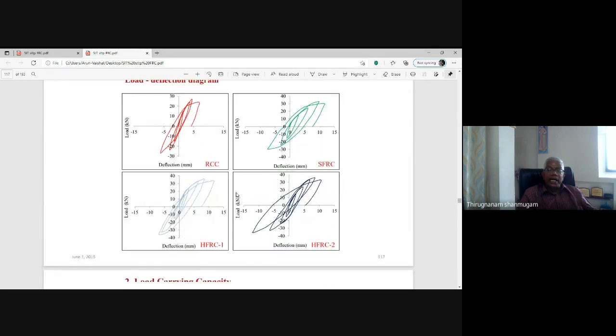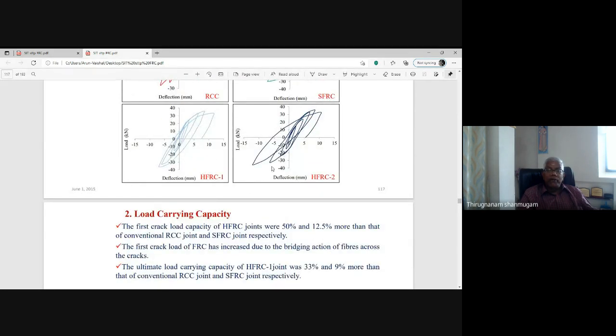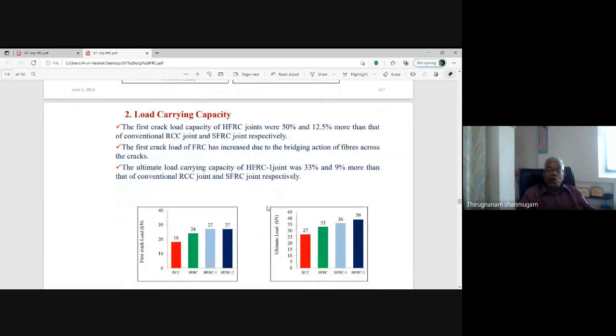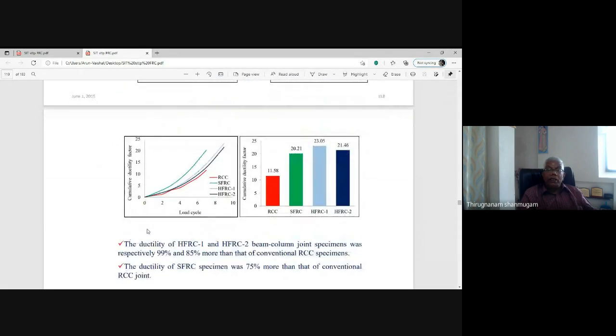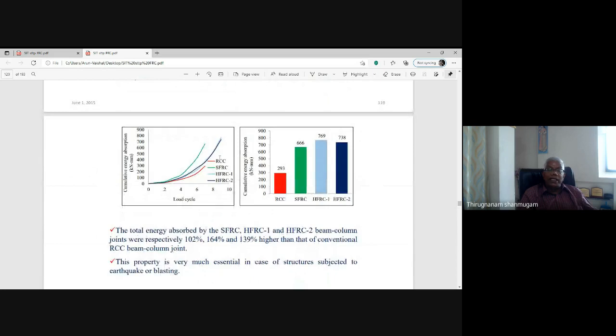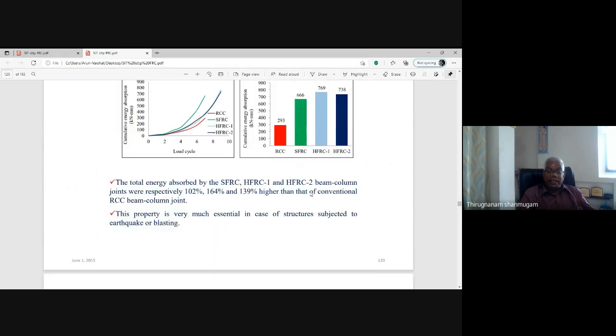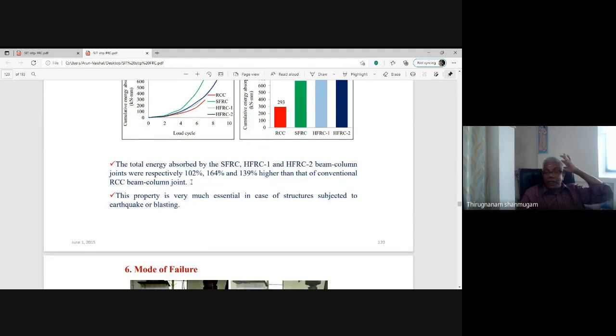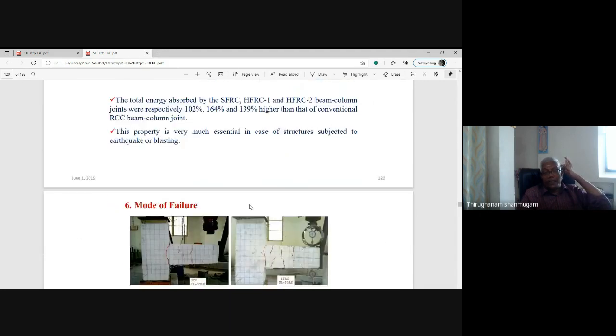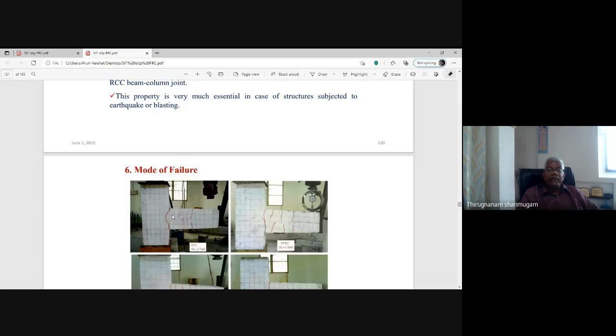Similar testing is done on the beam column joints, that is the load deflection behavior of the beams. The load carrying capacity is 18, 24, 27, 27 and 39 kN. The cumulative ductility factor is 11, 20, 23, 21, etc. Similarly, the energy absorption capacity is 293, 666, 769, etc. So about 100% increase in energy absorption capacity. The mode of failure is also different.